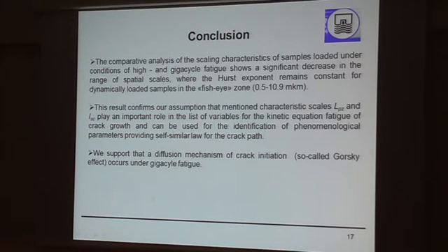This result confirms our assumption that the mentioned characteristics L_PZ and L_SC play an important role in the list of variables for the kinetic equation of fatigue crack growth, and can be used for the identification of phenomenological parameters, providing a self-similar law for the crack path. This supports the diffusion mechanism of crack initiation, the so-called Gorsky effect, which occurs under gigacycle fatigue.